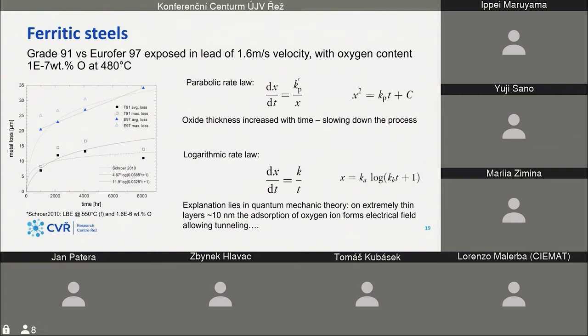Normal is a parabolic rate, where you grow some oxide that is increasing its thickness in time and slowing the diffusion processes. If you integrate this, you can get this parabolic law. But our data is impossible to fit with this type of law, so it's more like a logarithmic law. That has some explanation for extremely thin layers, in orders of nanometers, that lies in quantum mechanics, but it's definitely not our case. So it's maybe a combination of parabolic law at the beginning and some peeling of the magnetite that may appear in that way, but I have not enough points for that.